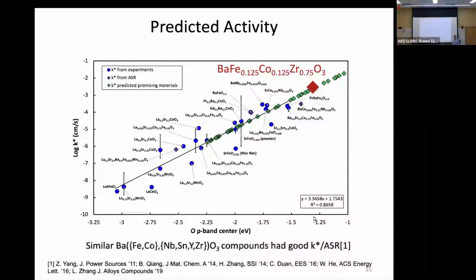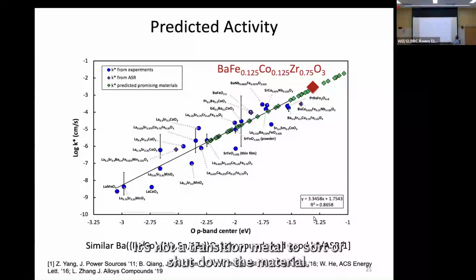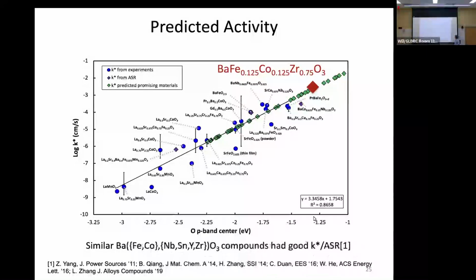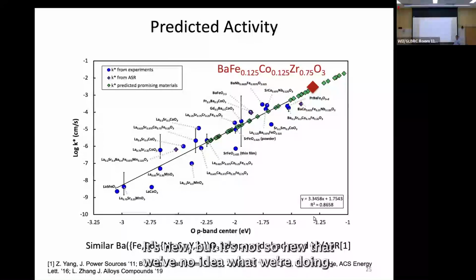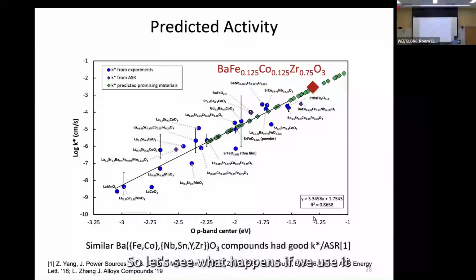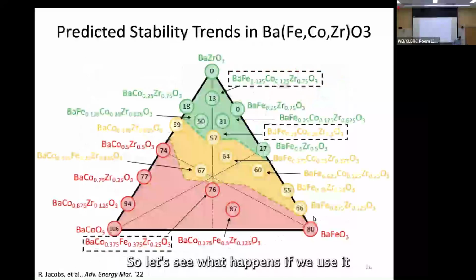But what was really interesting about this compound is it had a lot of zirconium. People had played with zirconium, but not that much, because they expected a lot of zirconium, it's not a transition metal, to sort of shut down the material. But these calculations predicted the material would actually still be pretty good. So we said, all right, this is kind of a safe compromise. It's new, but it's not so new that we have no idea what we're doing. We expect it to at least have some activity. We can change the zirconium content a little bit if we need to. So let's see what happens if we use it.